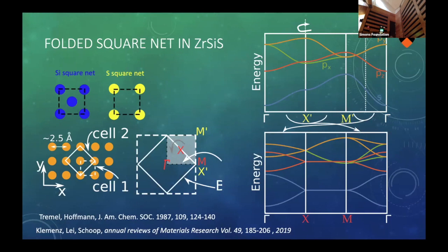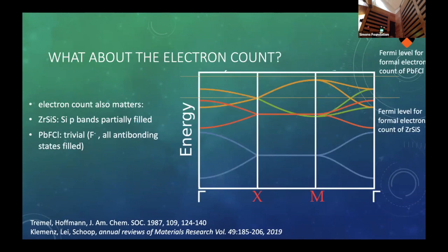So why do I care about chemical bonding? Well, what band folding does is create these crossings, or these points at the Brillouin zone boundaries, as has been discussed by Young and Kane and other people, but it does not put my Fermi level in the right place. If I just have 2 atoms per unit cell, I would have my Fermi level maybe up here, maybe down there, maybe over there, who knows where. But if I combine this with the electron count condition for a chemically delocalized bond, a hypervalent bond, then my Fermi level will be automatically pinned at the position where the band crossing is.